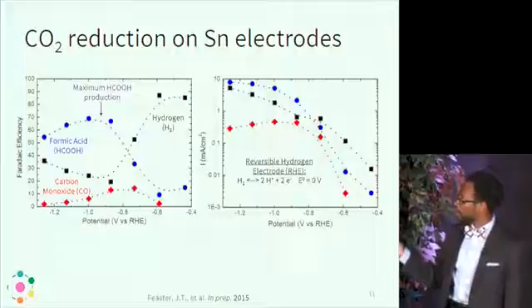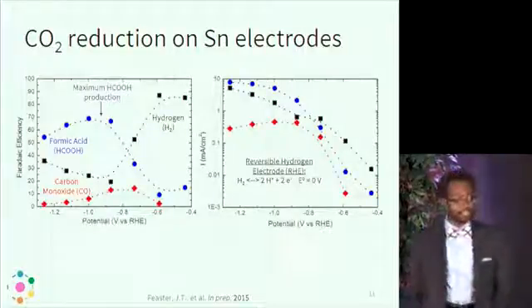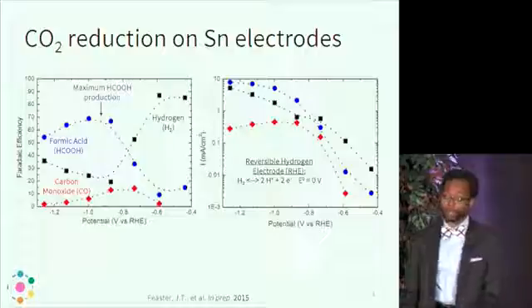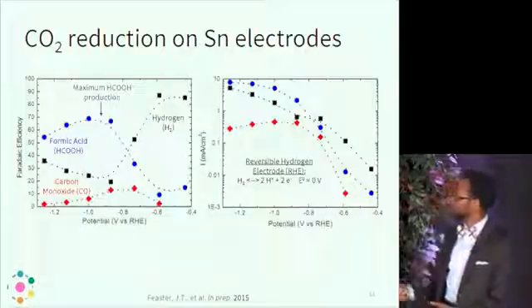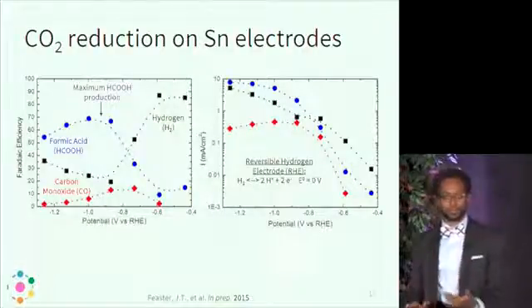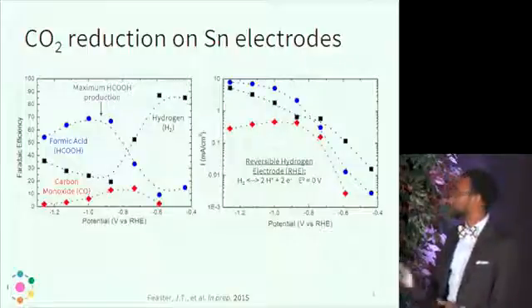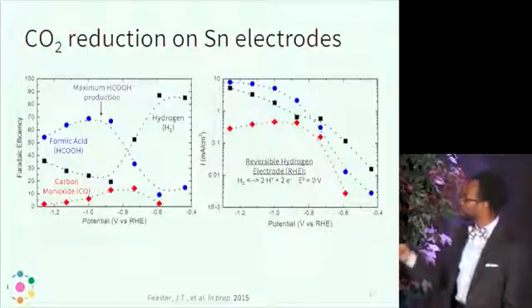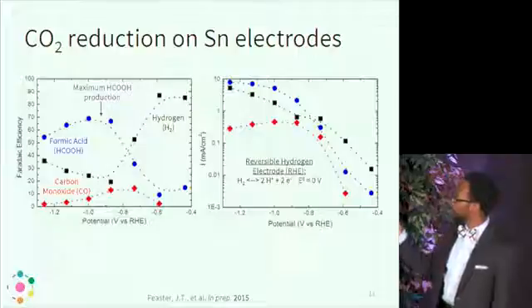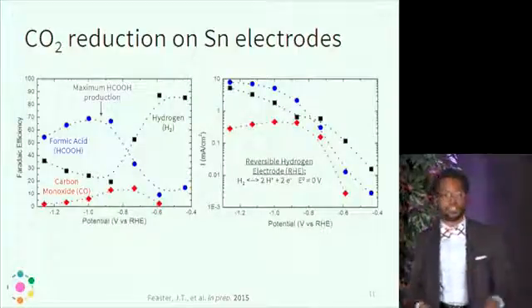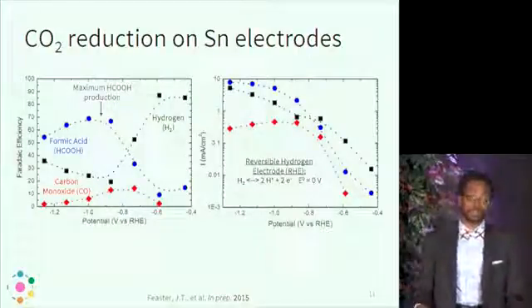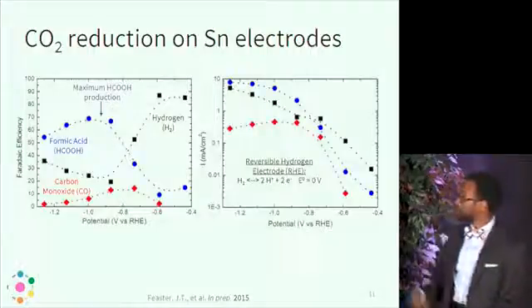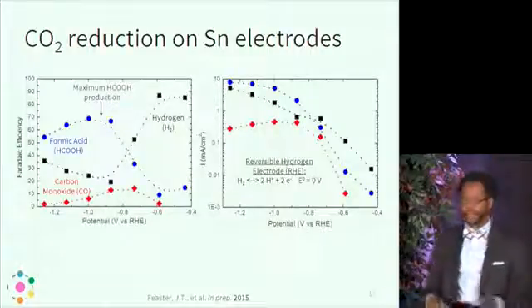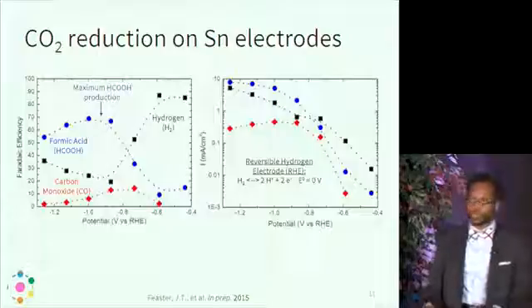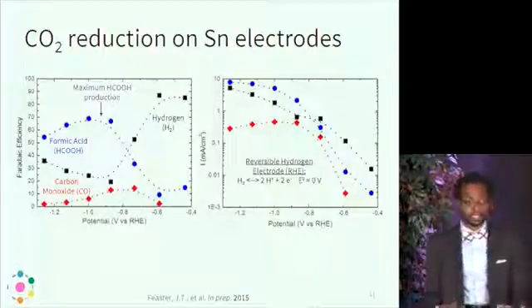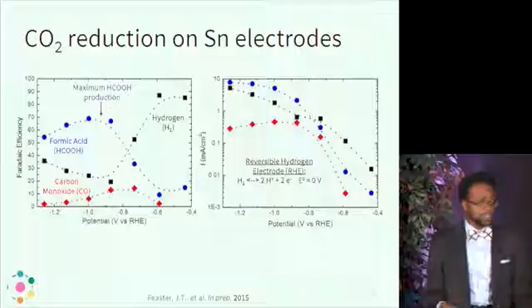On the plot to the right, you can also see our partial current densities, which really correlate to the products that we're making from CO2. So you can think of this as almost like the moles that we're able to produce from each of these, from tin, from CO2. And as you can see here, the formic acid starts to tail off, it starts to plateau, and that's really indicative of a mass transfer limitation for CO2 transfer to the surface, and that's what's capping our formic acid production there. So we're pretty sure that tin is able to make formic acid, and it seems like it's doing it just as much as we would expect it to.